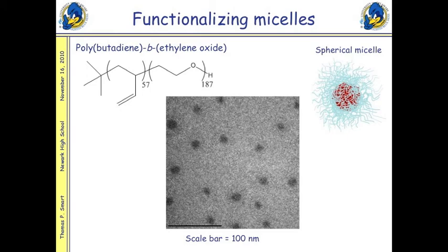So anionic polymerization is the name for it, and so you start off with an initiator in the solution, which is highly reactive and which kicks everything going. You have everything dissolved in solution, and you add your initiator, and that reacts with one butadiene unit, which then connects to the next one and the next one, and it goes on.